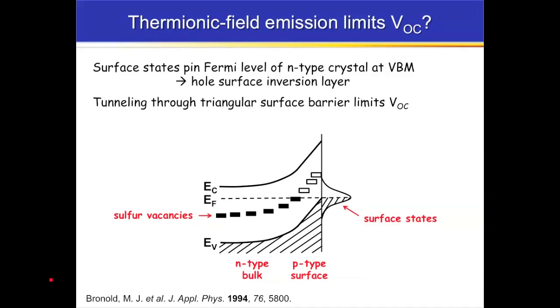And what these authors did is that they looked at single crystals that were N-type by Hall effect measurements. So you had a Fermi level that's close to the conduction band in the bulk. But they found that by ultraviolet photoelectron spectroscopy, the Fermi level was basically pinned at the valence band at the surface. And they invoked then this idea that in order to reconcile those two pieces of data, you've got to have band bending at the surface that's quite extreme in order to equilibrate the Fermi level here. And that's due to these surface states.